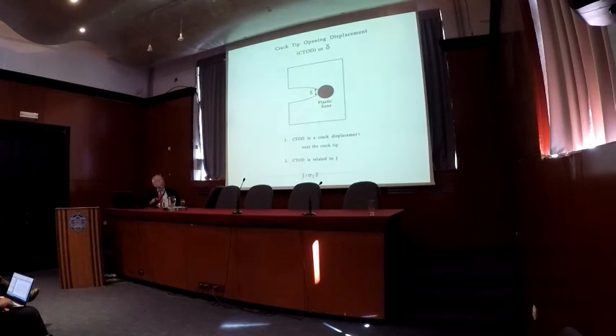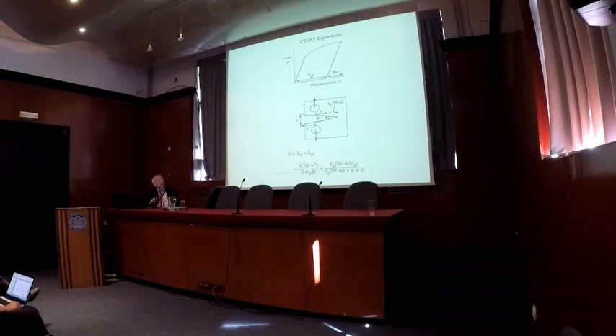CTOD is a displacement near the crack tip, and it's related to J. It's usually calculated like this, and there's a newer thing that has been developed, but this is the traditional way. In the low displacement that goes nonlinear because of plasticity, you have displacement that is elastic and displacement that is plastic. The elastic part is related almost to the Griffith G. It has the 2 sigma yield strength in it,